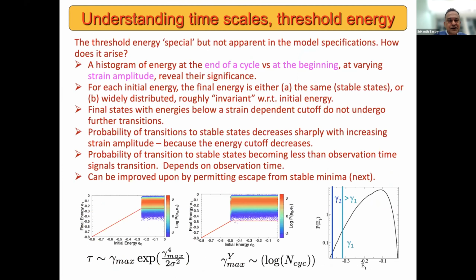Okay, now in order to try and understand why one finds this kind of behavior of the time scale required to reach the final state, one can ask a very simple question, which is, if I start with a mesostate of a certain energy and I apply one cycle of strain, what energy do I end up with? Okay, and in the simplest case, if nothing happens, and this is true for very deep energy minima, the final energy is the same as what you started with. Okay, and this is observed in these color maps by these red diagonal lines where the initial energy and the final energy are the same.